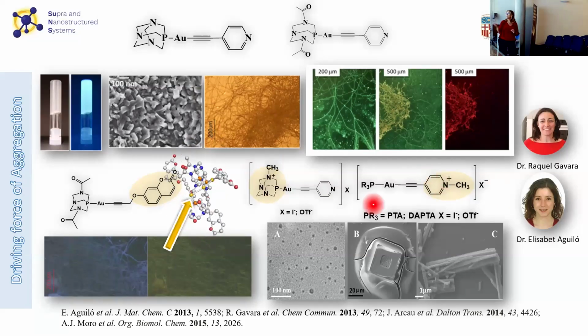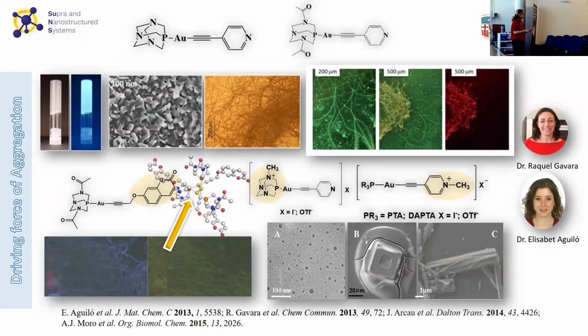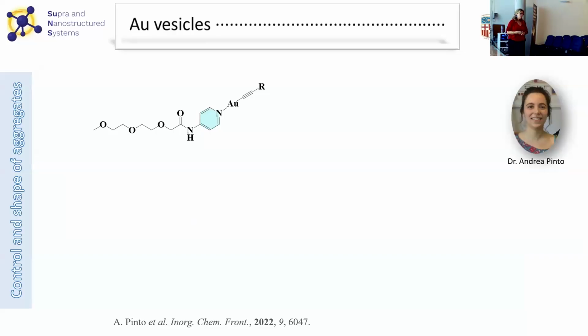And in these cases, we can observe that instead of these very long fibers, what we have is the formation of some vesicles, square-like structures, or some rod structures. So it is really relevant, not only the structure, but also if they are neutral or if they have a positive charge in any place of the molecule, modifying the resulting morphologies. Okay, but this, as I said, was a little bit of serendipity. So I don't know if it is your case, but at least in our case, we feel more comfortable if we can have some control or we can design what we want to happen in the lab. So we decided that maybe a rational design could make us feel a little bit more comfortable.